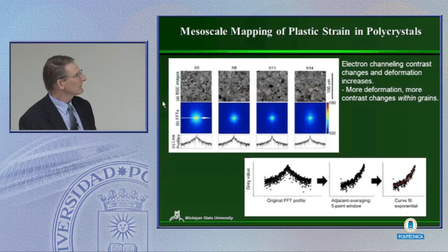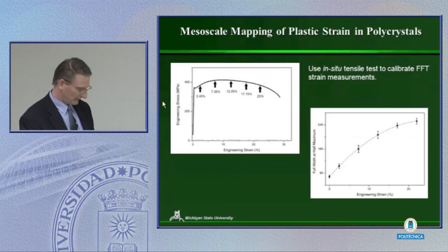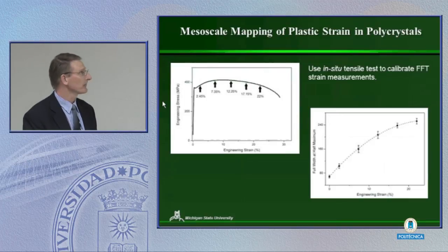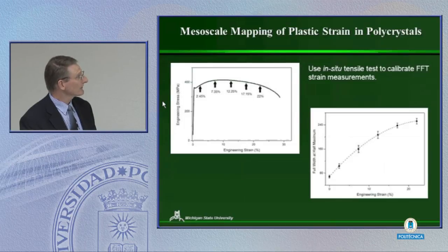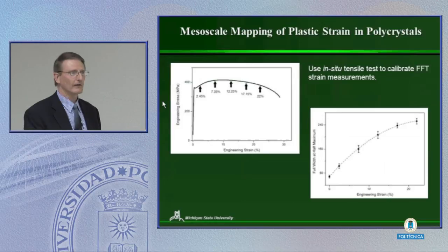And what we said is, if there's a change in this contrast like this, maybe what we can do is do a Fourier transform on that. And when we did that, it was very, whoops, sorry about that. It was very clear that the Fourier transform changed because the frequencies in the images were changing. And again, these are fairly low magnification images. That's 100 microns there. And if we take a trace across those, we can actually turn around and measure the full width at half maximum. We do a bit of cleaning up to do that, which now gives us something that says, okay, the full width at half max is going to change as we deform the material.